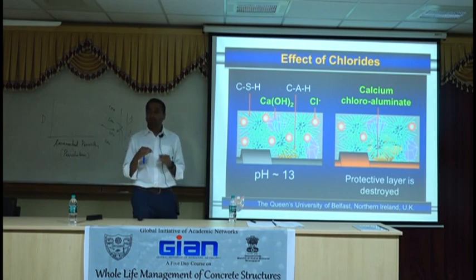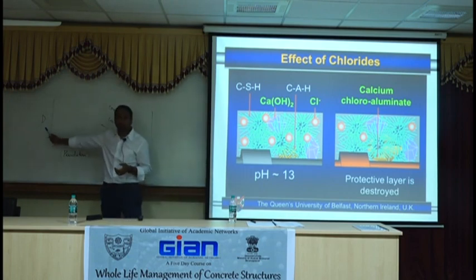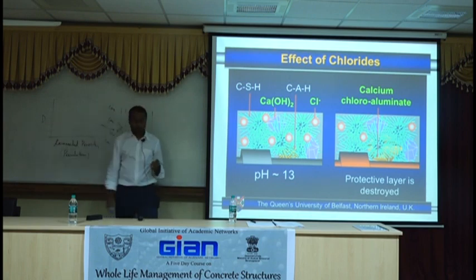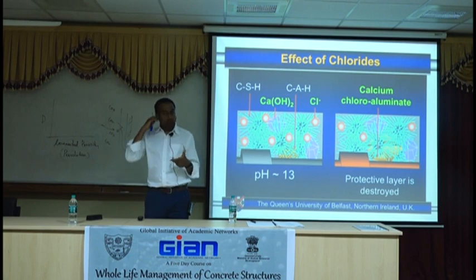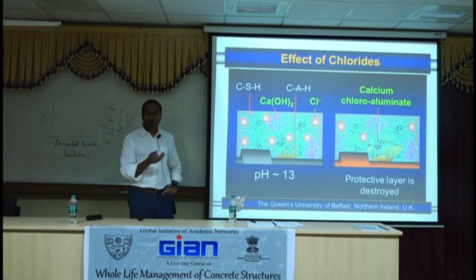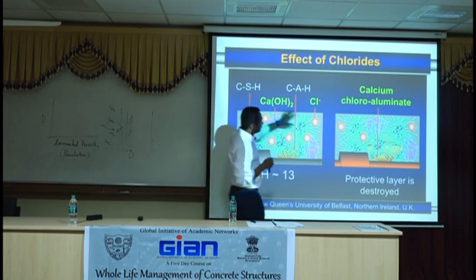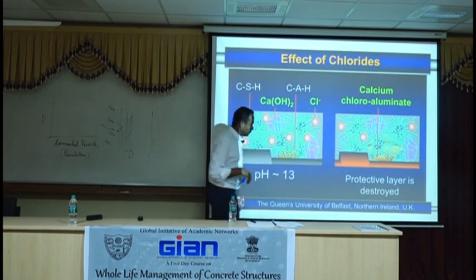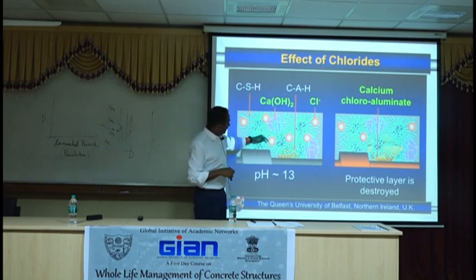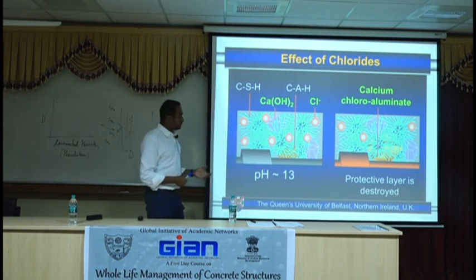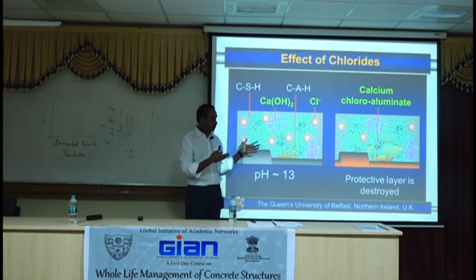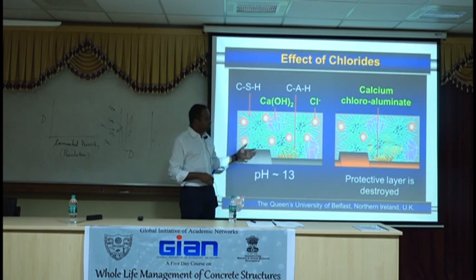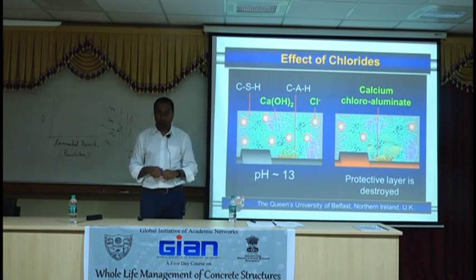It again is a two-part thing. There's a transport controlled by the concentration difference and the gradient diffusion, and there's a reaction phase. Chlorides are quite difficult to model. They are mathematically challenging to model, but it's not impossible. And when it forms calcium chloroaluminate, which is the Friedel salt layers, and if it manages to exceed a certain value of chlorides that the chemistry can balance, called the chloride threshold, it will then destroy the passive layer of steel. Bear in mind, I said to you that it can even go into cast iron, which means it can attack steel quite easily.